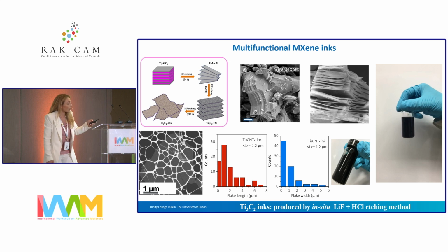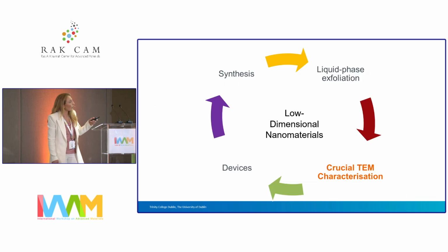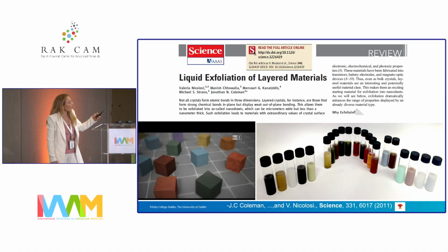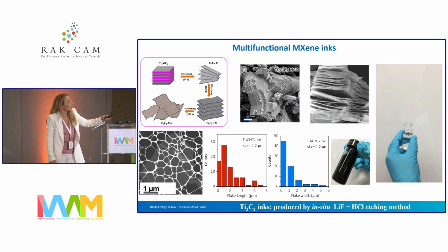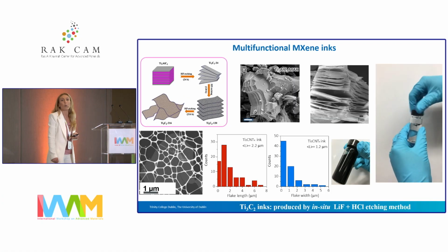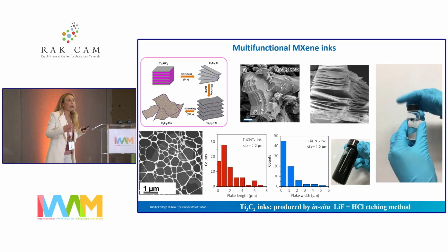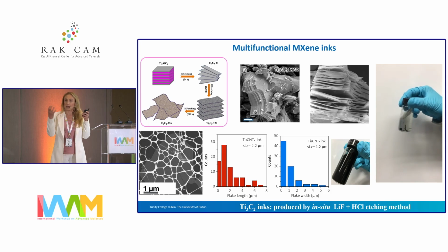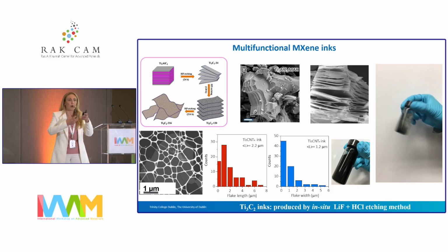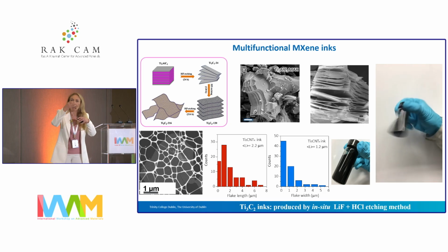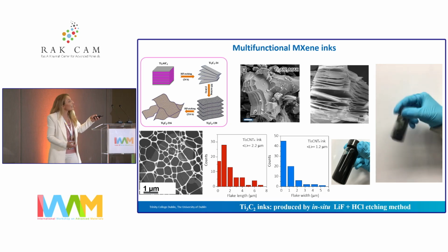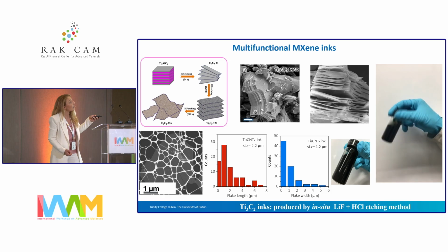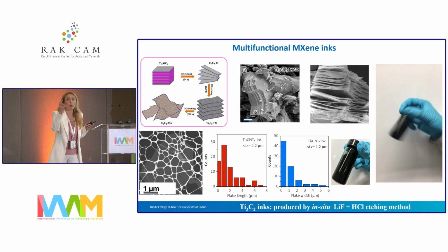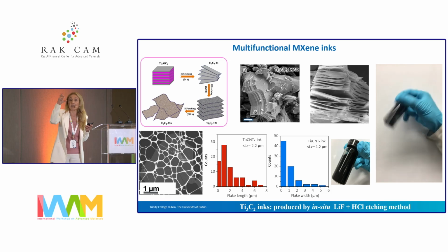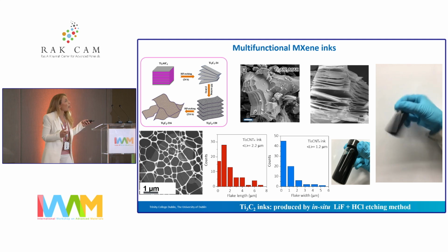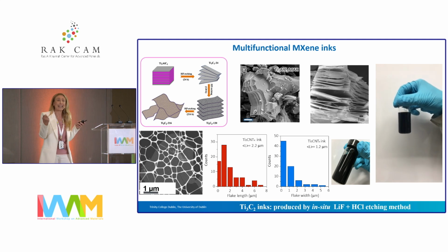Once you do that, this becomes extremely well dispersible even in water. So forget about all the high boiling point organic solvents that you need for more classical van der Waals layered crystals. In this case, all you need is water, and there you get a very nice stable dispersion. What I will refer to later on as an ink.